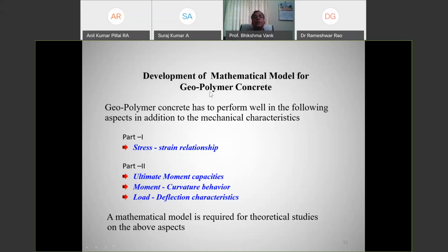Development of mathematical model for geopolymer concrete. What we have done is we have done stress strain relationships for each grade of concrete, and from the stress strain relationships which are obtained, we developed a model for your stress strain curves, and these models are superimposed onto the moment carrying capacities and load carrying capacities for the flexural behavior of the beams.